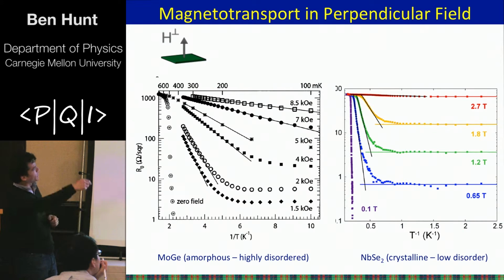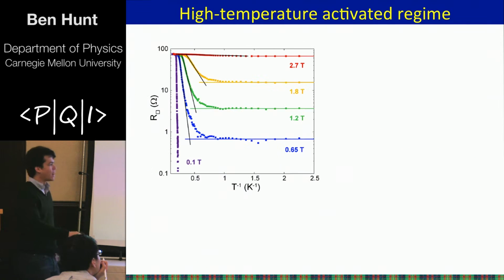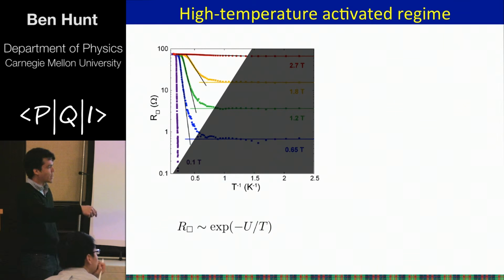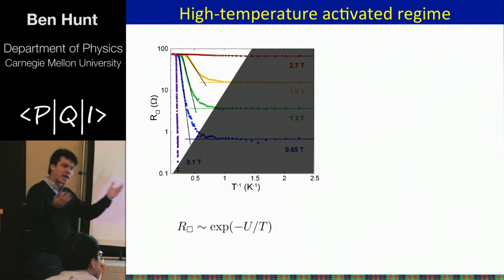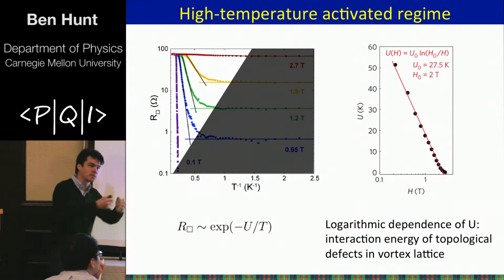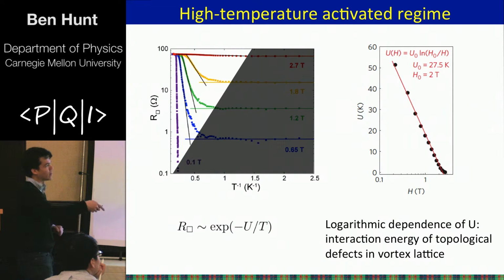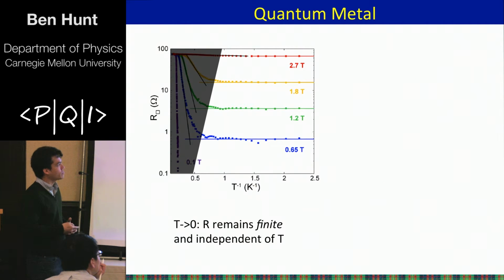So just some more details about this. If we look at the high temperature regime, the resistance is actually activated. And we can understand that looking back at these papers from the 1990s in terms of basically a logarithmic dependence of this activation energy on magnetic field. That has to do with the properties of the vortex lattice and creating dislocation, anti-dislocation pairs in the vortex lattice. But this is pretty well understood. And then this is the feature that I want you to remember about the talk, which is that the resistance remains finite and independent of temperature as we go to low temperatures. The behavior with magnetic field is the important thing, an important new contribution that we made.